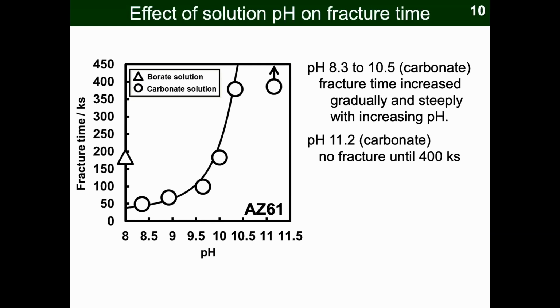So here I show you the effect of the solution pH on the fracture time. As you can see, fracture was obtained in the solution of pH 8.3 to 10.5. And when you increase the pH, fracture time gradually and steeply increases. At pH 11.2, this solution had no fracture until 400 ks. This is enough for the EAC.